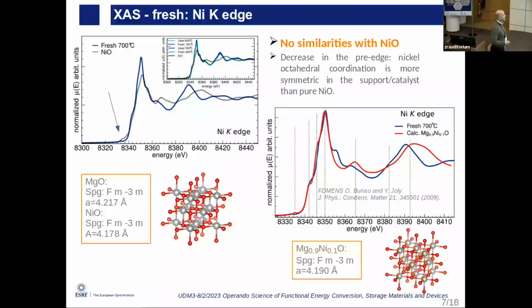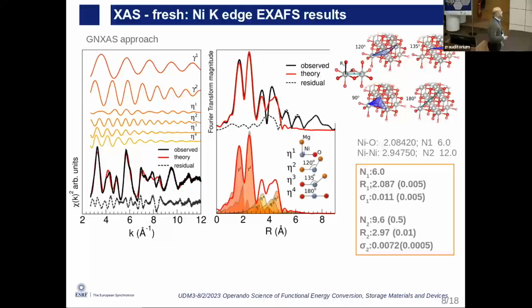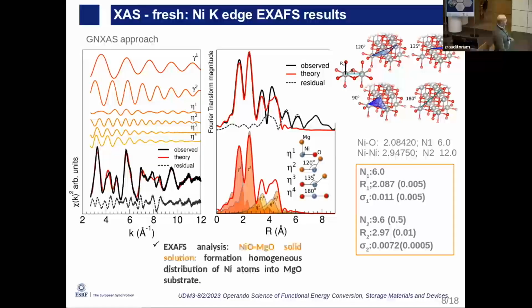And then we tried to give this kind of ratio of the nickel. In fact, we have 10% of nickel, so we cannot think differently. To confirm this further, we did an EXAFS study. Since we use an GNXAS approach, we could decompose the model, starting from the structure we proposed before, and using just two shells, we could fit our data up to 5 angstroms. That is quite interesting, but since the multiple scattering is the fingerprint of the structure, we can easily conclude that the nickel goes in this kind of environment. And since the amount of nickel is just 10%, we can also think that it's a quite homogeneous distribution of nickel inside the oxide.